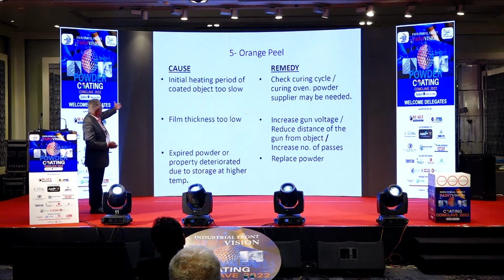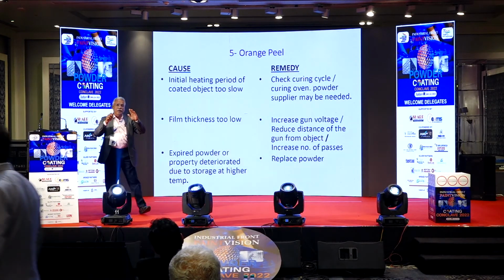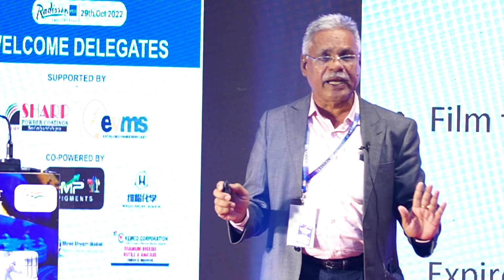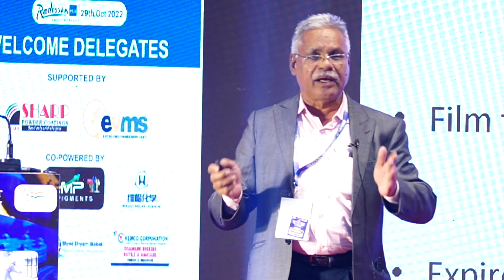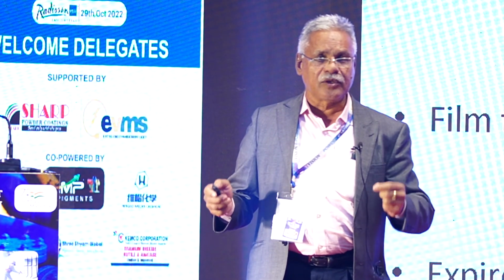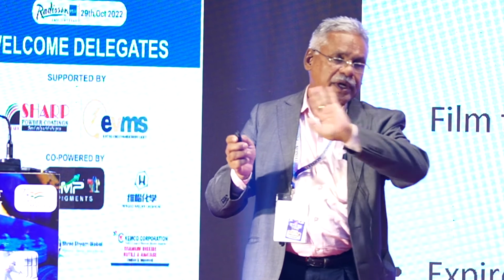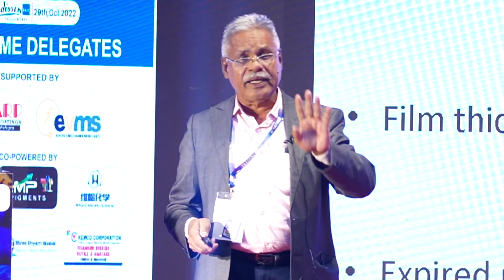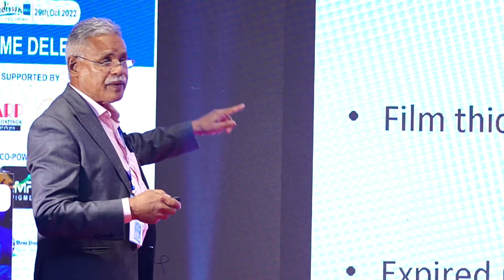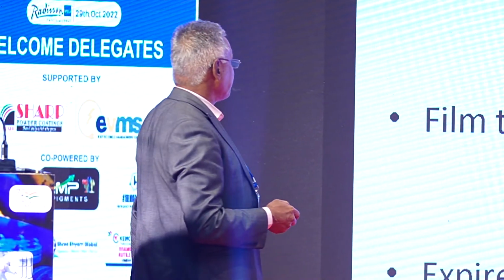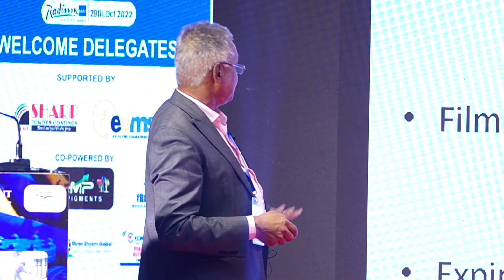Then orange peel: the initial heating period of the coating object is low. What is it in powder coating? First you heat the empty oven to full temperature, 180 degrees, then open the oven and push the stand, the hanger with the coated components, immediately in. In that time the temperature drops by about 20 degrees and immediately picks up. If you start from 0, then this problem will come. Orange peel will come because it starts from low temperature to high temperature. Film thickness too low: if coating thickness is less than 70, this orange peel can also come.